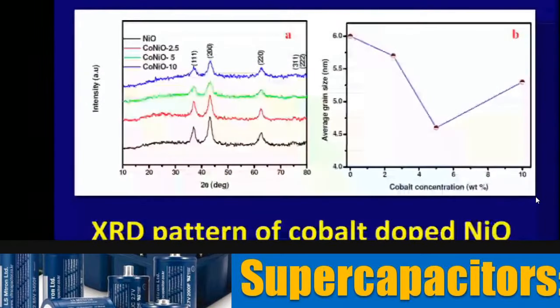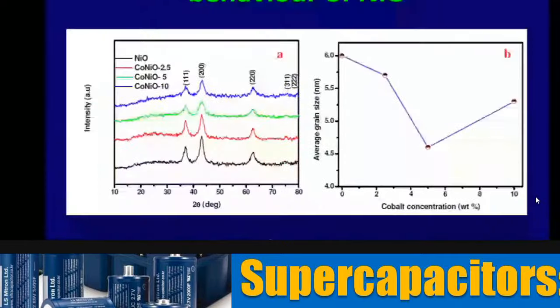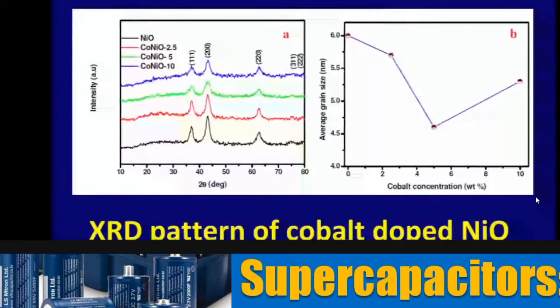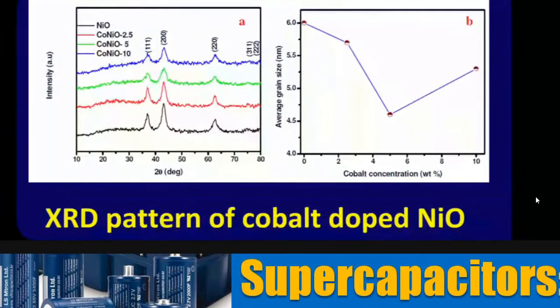So, the next question we ask is, if you have a material, is there some possibility by which the capacity can be improved? One method would be to increase it by adding another transition metal ion, or probably add a metal which will improve the series resistance. We have tried both. We have tried cobalt doping into nickel oxide and also silver doping into nickel oxide. You can see that when you dope it, it is only cobalt replacing nickel, because the XRD spectrum that you see on the left hand side does not show any peaks other than nickel oxide peaks, which means that I have a cobalt doped nickel oxide. And you see that with 5%, we get the average grain size to be very small, and that gave us the best performance.